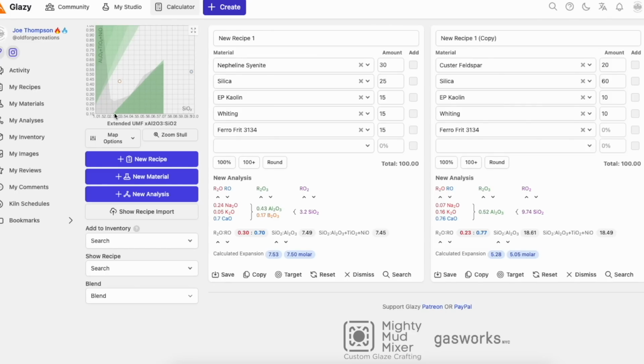You have increasing silica, and this has fallen so far off the edge that it's actually outside the drawn part of the map. There is so much silica in relation to those fluxes that, this green line here is the under fired, will not melt kind of line. So with that much silica in, there isn't enough flux to melt it, particularly with no boron in it. There's just no hope of that being a glossy cone 6 glaze. You can't put 60% silica in a glaze and expect it to melt. The thing is, ChatGPT does not understand that.